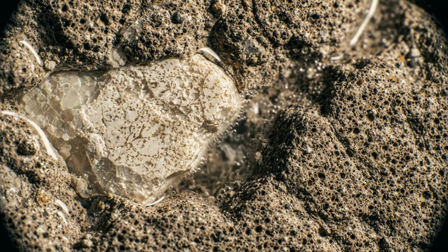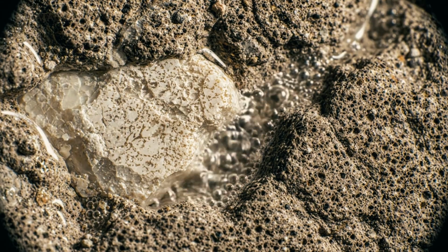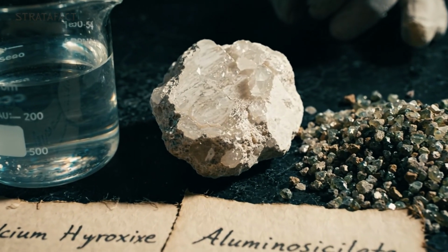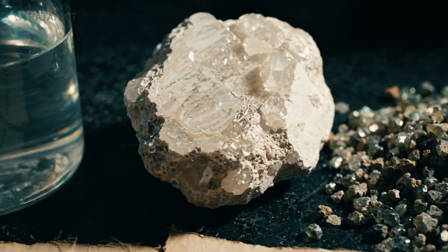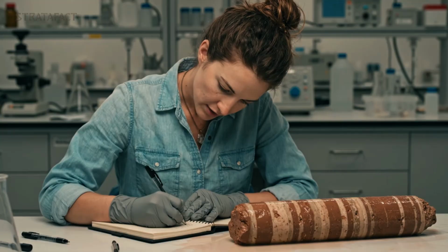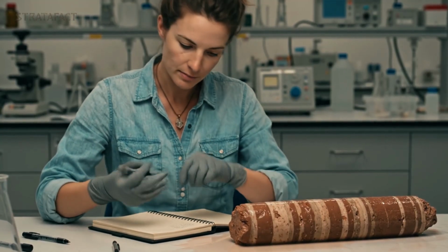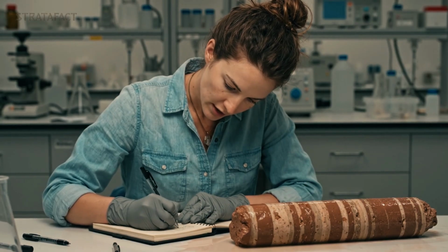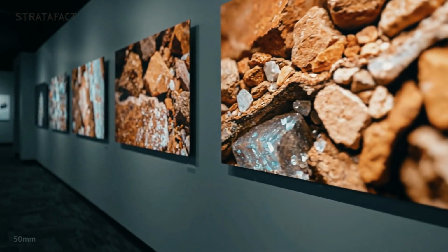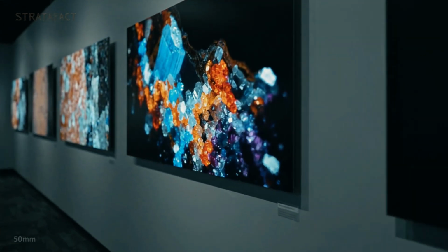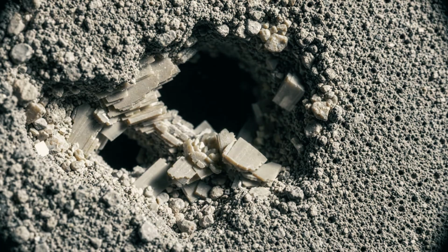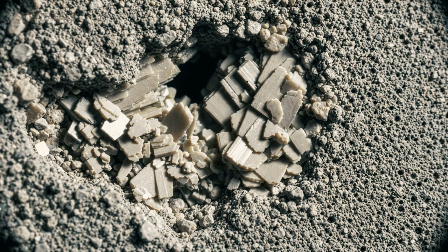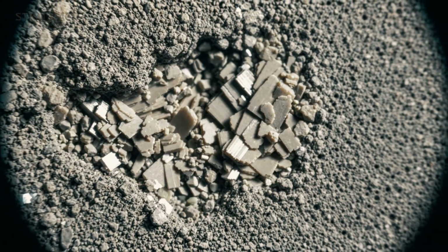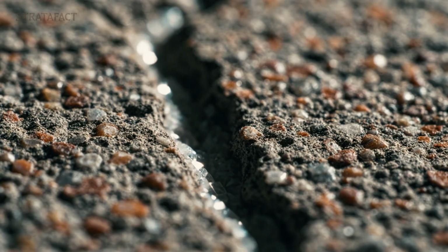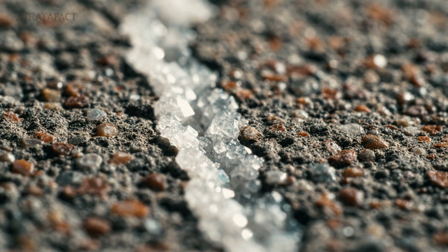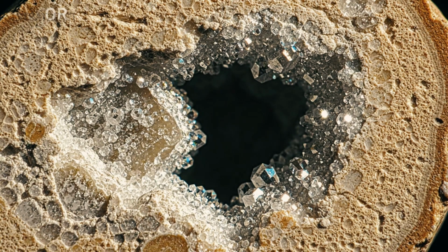The physical process at a lime clast is specific. When seawater reaches an unreacted lime particle embedded in the set concrete matrix, the calcium hydroxide at the surface of the clast begins to dissolve into the water. The dissolved calcium combines with the aluminosilicate compounds from the surrounding pozzolana, compounds that remain reactive in the matrix long after the initial cure. The reaction nucleates tobermorite crystals at the interface between the lime clast and the surrounding material. Those crystals grow outward into any available space, pores, microcracks, the void left as the lime clast itself dissolves, filling and reinforcing the exact locations where structural weakness was developing. The defect becomes the repair site.